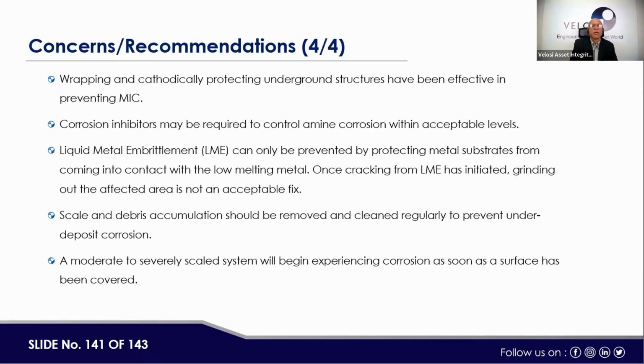Liquid metal embrittlement can only be prevented by protecting the metal substrate from coming into contact with low melting metal. Once cracking from LME has initiated, grinding out the affected area is not an acceptable fix. Scale and debris accumulation should be removed and cleaned regularly by flushing to prevent under-deposit corrosion. A moderately to severely scaled system will begin experiencing corrosion as soon as a surface has been covered.